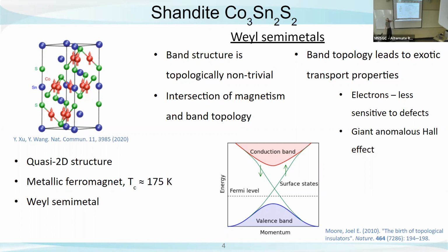If we look at this image below on the bottom here, this is actually for a topological insulator, but most normal materials that you see will have kind of like this parabolic look to them in their band structure. And for a topological insulator, they start to become more linear, and you get this overlap of your band structures. And so the cool thing about a topological insulator is that on those surface states, you have those bands that are overlapping. But with a Weyl semimetal, instead of just happening on the surface, it starts to happen in the bulk. So you're getting it in the whole material instead of just on the surface, which allows for electrons to be more mobile and free moving, which is the property that we're looking at because we're super interested in that band structure along with magnetism.